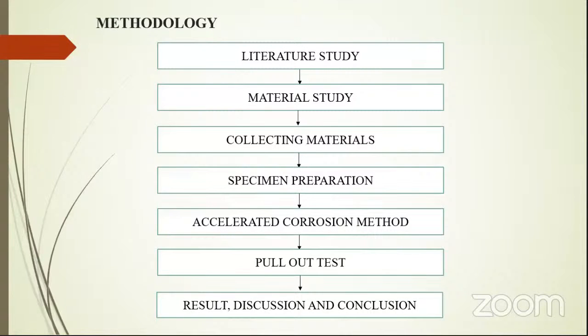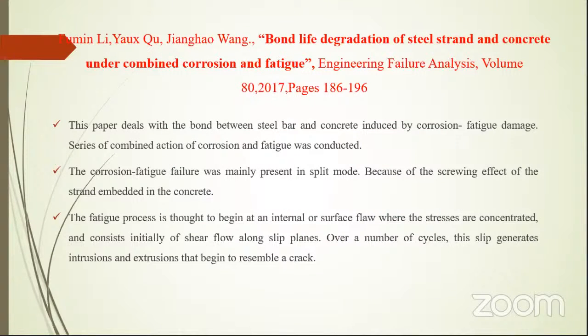Next, our methodology, from the start: literature study, material study, collecting materials, specimen preparation, then accelerated corrosion method, pull-out test, next result discussion and conclusion. Our first literature is about bond life degradation of steel strand and concrete under combined corrosion and fatigue. This paper deals with the bond between steel bar and concrete induced by corrosion fatigue damage. A series of combined action of corrosion and fatigue tests was conducted. The corrosion fatigue failure was mainly present in split mode because of the screwing effect of the strand embedded in the concrete. The fatigue process is thought to begin at an internal or surface flaw where the stresses are concentrated and consists initially of shear flow along slip planes. Over a number of cycles, this slip generates intrusion and extrusion that begin to resemble cracks.